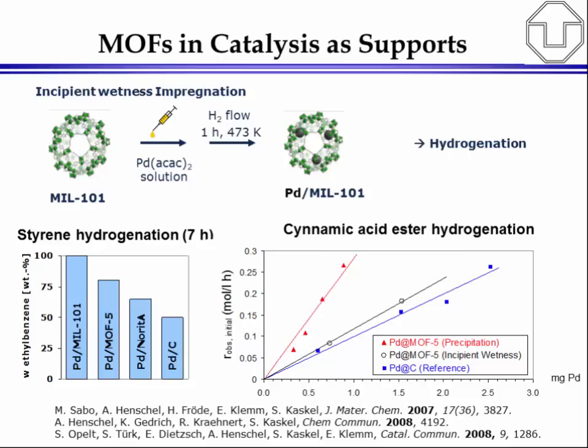And these catalysts have a very good performance, for example, in hydrogenation reactions, like you can see on the left-hand side, styrene hydrogenation, but also in cinnamic acid ester hydrogenation. So very high activity. And in the next slide, we can see that